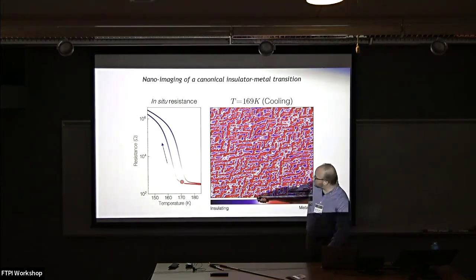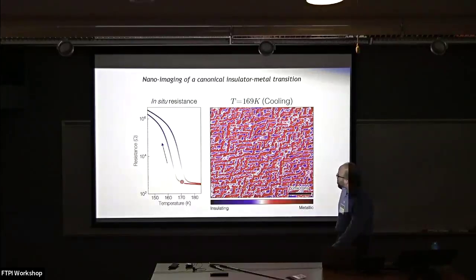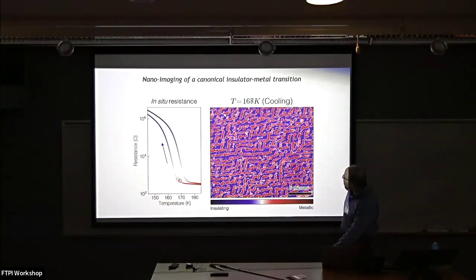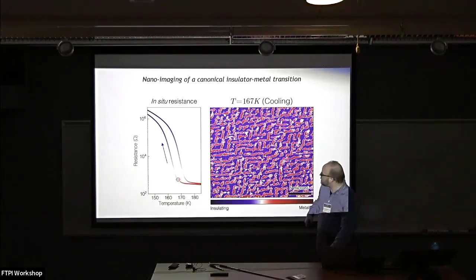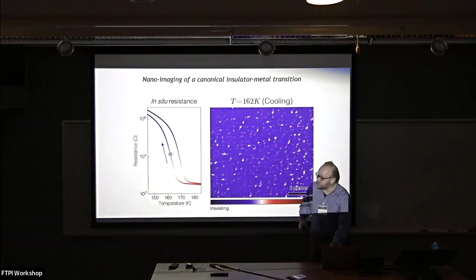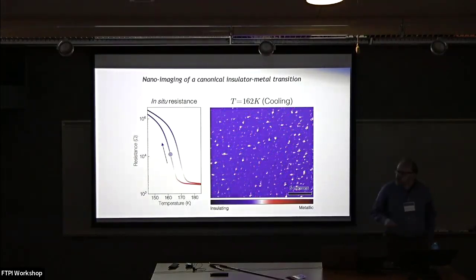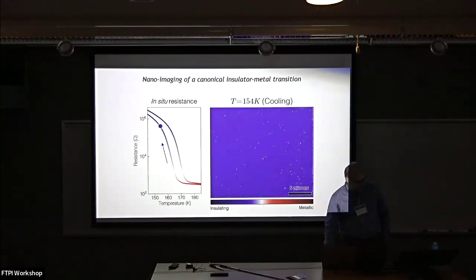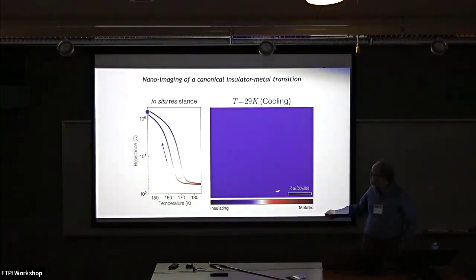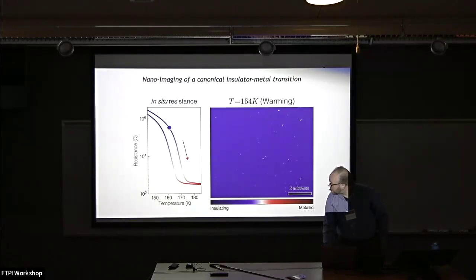And maybe right about here at this inflection point, there should be a percolation event that happens, which is something that resistive measures would see in real space. We can kind of witness that as we break up the metallic phase into these isolated islands. And if we cool sufficiently, and we really do have to cool a great deal, we can at last, let's say, get out of the spinodal region and start to get rid of all the metallic phase. Although there are some little domains that hold on for dear life, clearly. Until finally, push it down a bit lower and we achieve homogeneous insulator. No surprise there, but it's what was in between these two phases that is maybe a little bit surprising. Okay. Now, of course, we can play the movie in reverse.